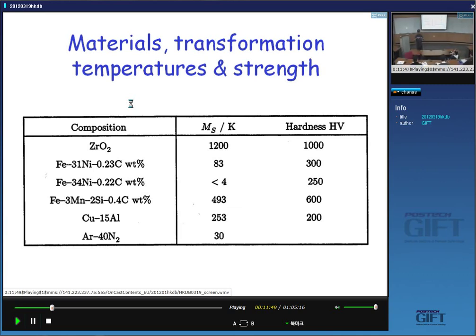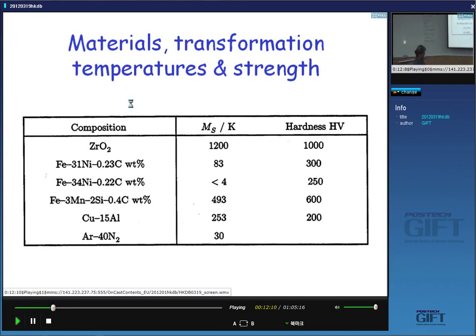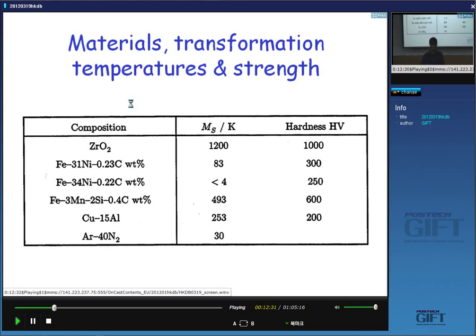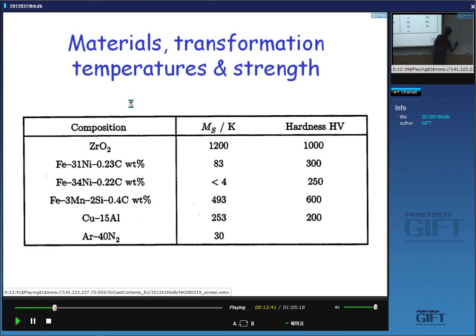That's why carbon in austenite causes very little hardening, just like nickel in austenite causes very little hardening — because it causes a uniform expansion. A tetragonal strain field, on the other hand, has a very strong interaction with the shear strain fields of dislocations. After all, a dislocation is about shear, not volume change. So there is a strong interaction with dislocations.